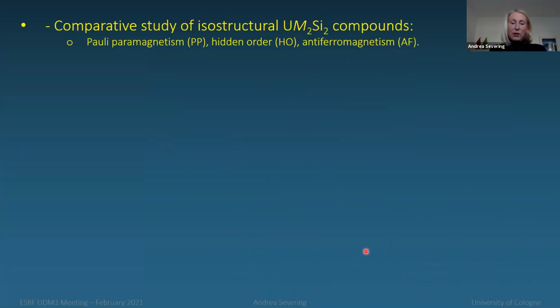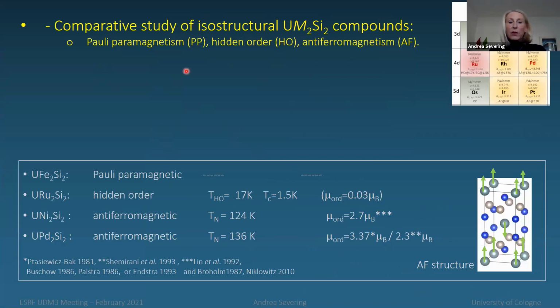So now to our study. It's a comparative study of isostructural compounds like uranium ruthenium-2 silicon-2. And we are looking at compounds that have very different ground states. We have here our uranium ruthenium-2 silicon-2 compound. This is the hidden order compound with its transitions. We're comparing it with a Pauli paramagnet, uranium iron-2 silicon-2. It shows enhanced Pauli paramagnetism. It doesn't order down to lowest temperatures.